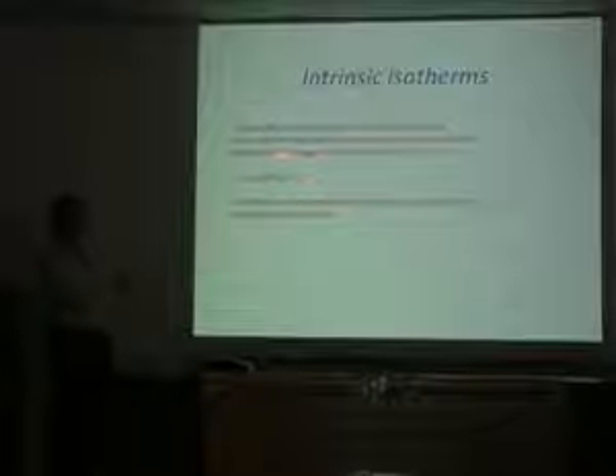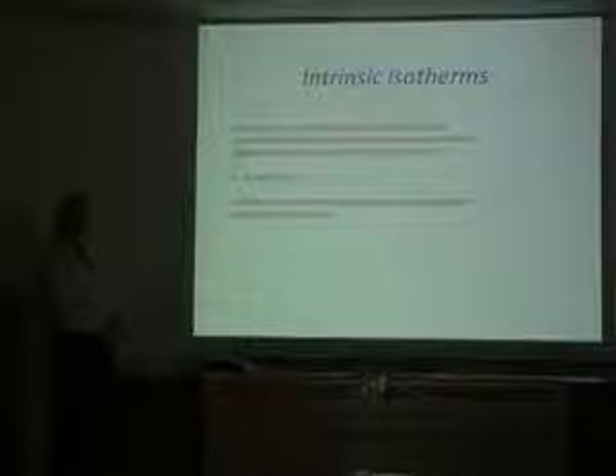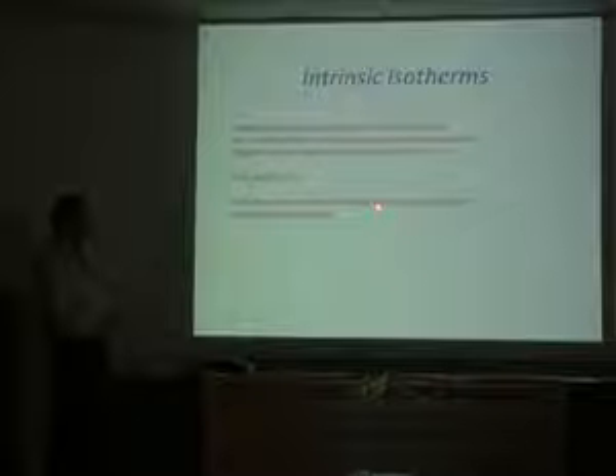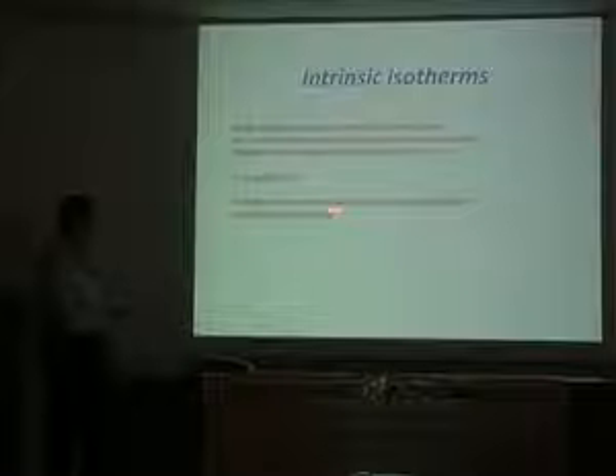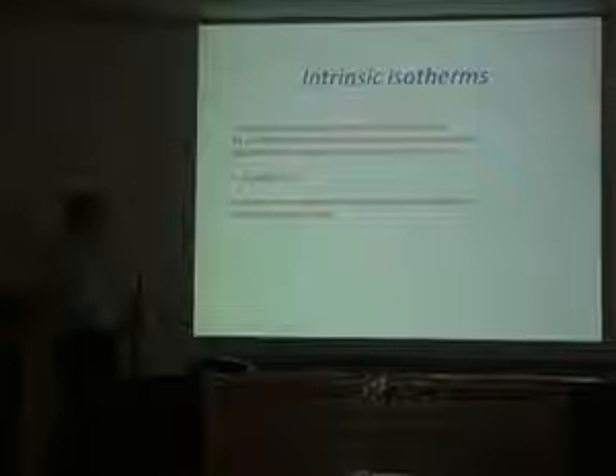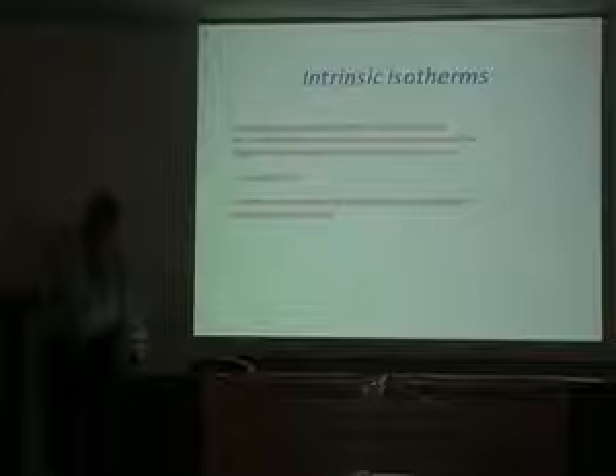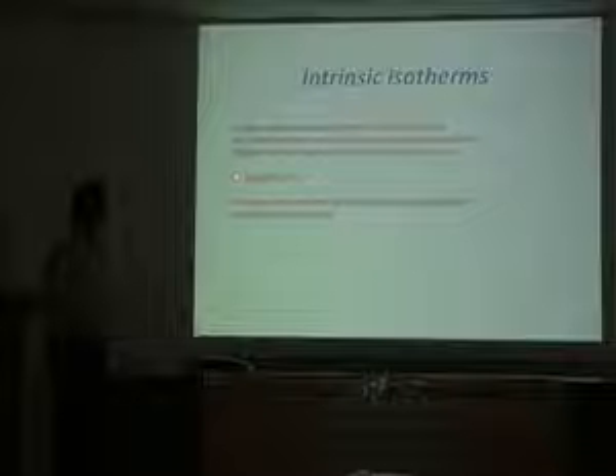So, as I said, empirically, the intrinsic isotherms can be described by a stretched exponential with an exponent that depends on the magnitude of the T-jump, such as this kind of KWW function, and indicates a non-exponential decay, but the data set that we have is insufficient to establish definitively that this is the correct way to describe the behavior. Delta is that volume departure from equilibrium, the V minus V infinity over V infinity.